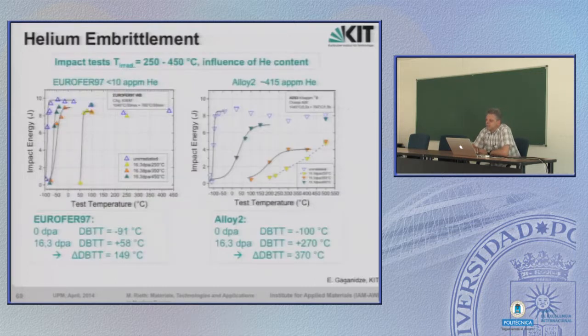Then the same study has been done with two similar types of steels, where one steel produces almost no helium under irradiation and the other steel produces 400 atomic parts per million helium. That's a lot, by the way. Same conditions.